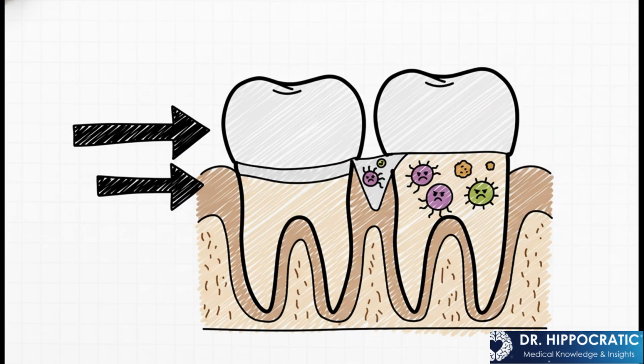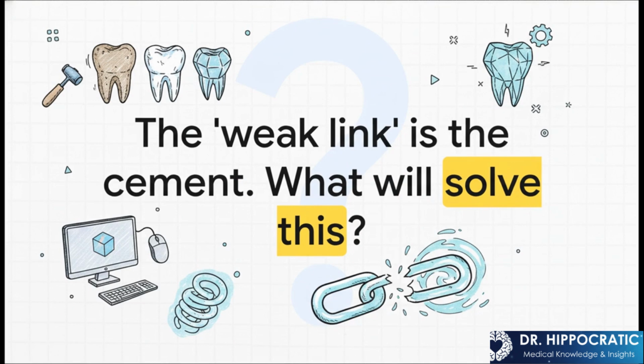So what does that actually mean in the real world? Well, over time, that much softer cement can slowly wear away right at the edges of the crown, and that creates a tiny gap or defect. This is exactly why the incredible accuracy of CAD/CAM milling is so important. A better, tighter fit means a smaller gap, which means less exposed cement, and that all adds up to a stronger, longer-lasting restoration.